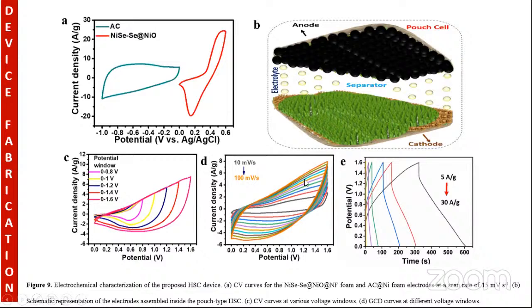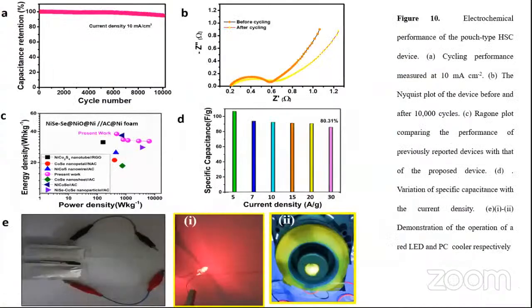Figure D shows the CV of the device from 10 to 100 millivolt per second scan rate. Here you can see the pseudo-rectangular kind of shape, which is characteristic of a hybrid material. Figure E shows the GCD curve of the device from 5 to 30 ampere per gram. Here the steep slopes also indicate the hybrid performance of the device. Now, coming to the cyclic retention, we found around 92% capacitance retention after 10,000 charge discharge cycles, which is highly desirable for any kind of device.